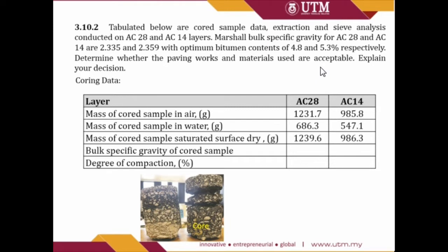Okay, this is the data for coring works. So the core samples were taken to the laboratory and determined for bulk specific gravity by taking the mass of core sample in air, then mass of core sample in water, and then mass of core sample saturated surface dry.